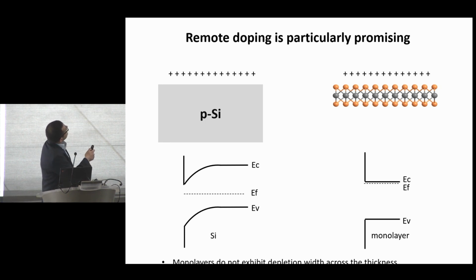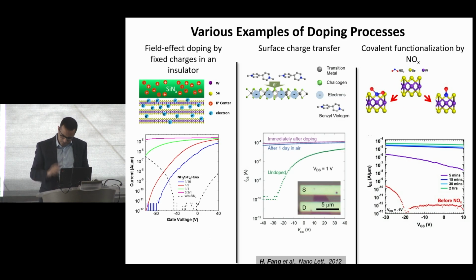So while in this case, some of the positive charges that are placed on the surface are compensated by the depletion charges of the semiconductor, and you can keep depleting it more and more, over here, whatever fixed charges you put on the top will be compensated by the electrons or holes that you will bring in by the inversion charges or accumulation charges in your semiconductor. So this is a very promising approach for materials that are fully depleted, or in this case, materials that are at the thickness scaling limit, where there is no depletion depth. The depletion width is just limited by the thickness of the material.